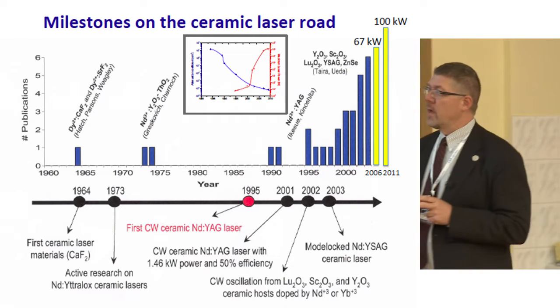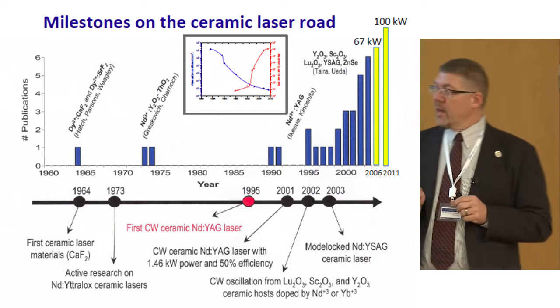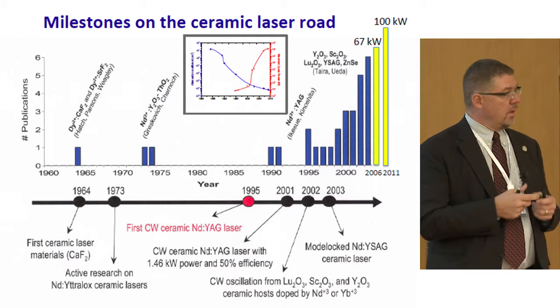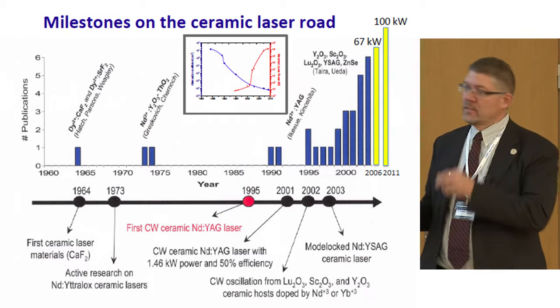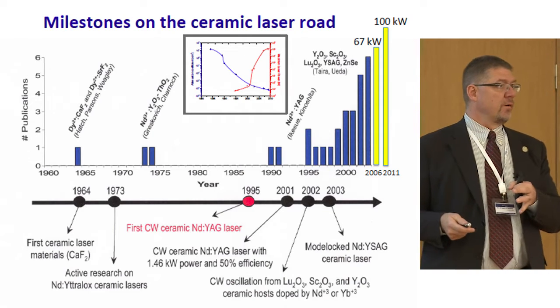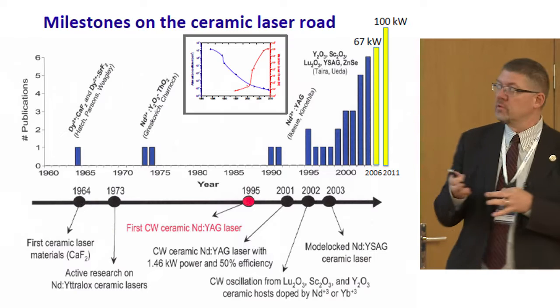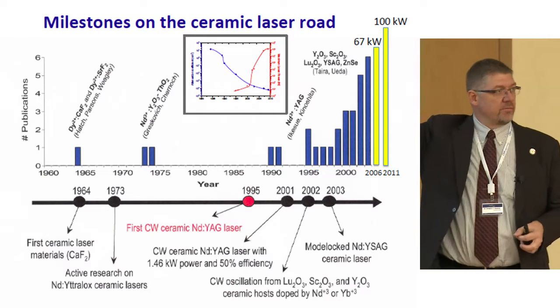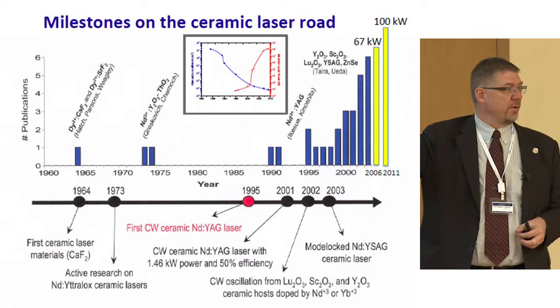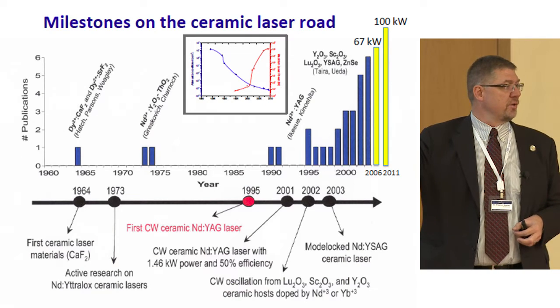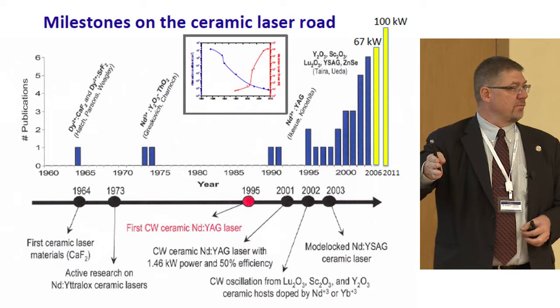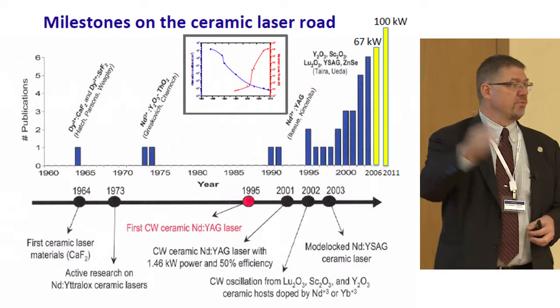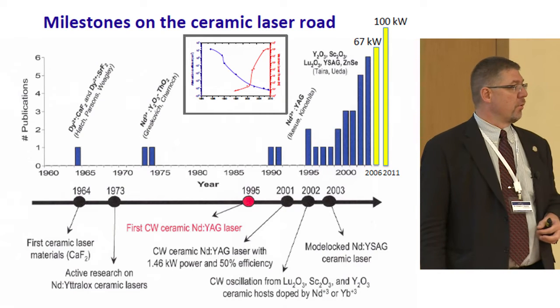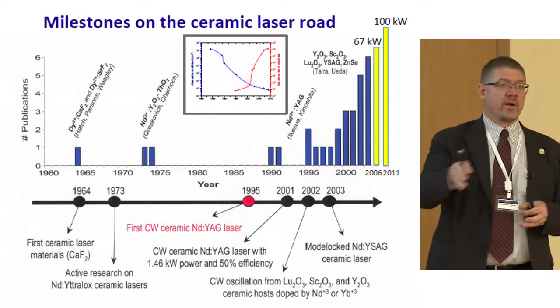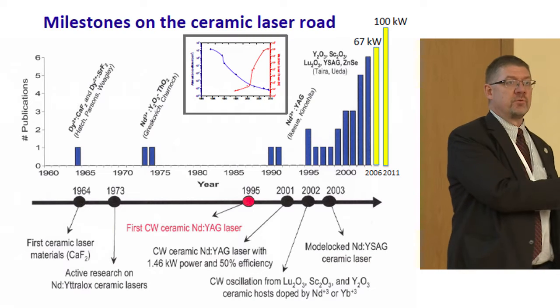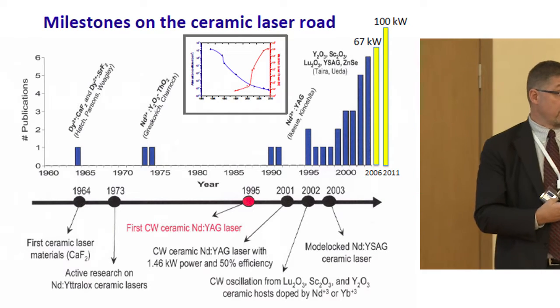And they had YAG coming out of Hitachi Mining and several other companies that was being grown single crystal. But as you saw from the picture, in order to get below 200 nanometers, fifth harmonic, as we saw with one of the posters yesterday, that means you start with 1064, then you do second harmonic generation to 532. Probably throw away 50% of your energy there. And then you go from 532 to 266 and throw away another 50%. And then from 266 down to 213 or 193 nanometers. A very, very inefficient process to get into the sub-200 nanometer region for photolithography for electronics.